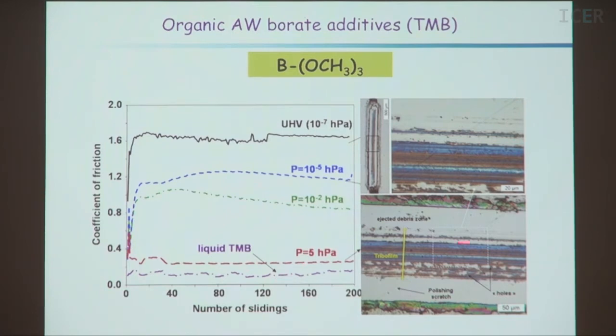And you can see here the tribofilm, which is formed in the wear scar. This blue colored area is an optical micrograph of the tribofilm. This tribofilm protects the surface from wear and decreases the friction. This is typically the role of the additive in the lubricant: to decrease the friction and to protect the steel surface from wear.